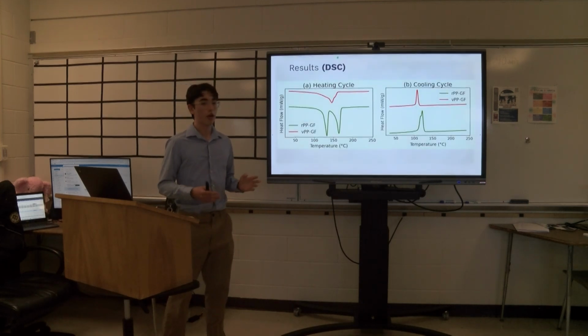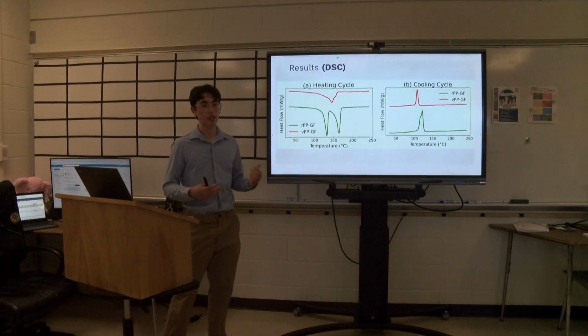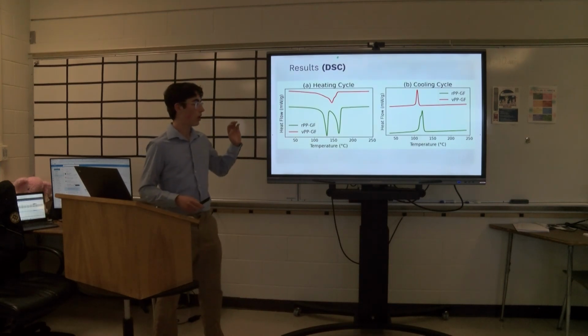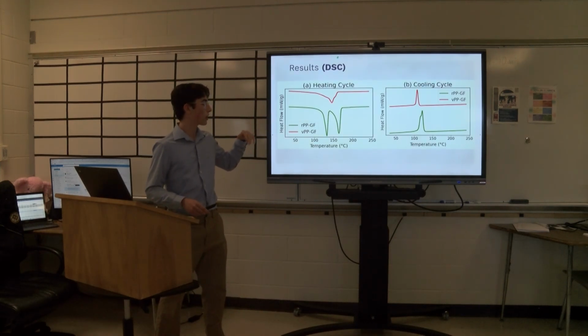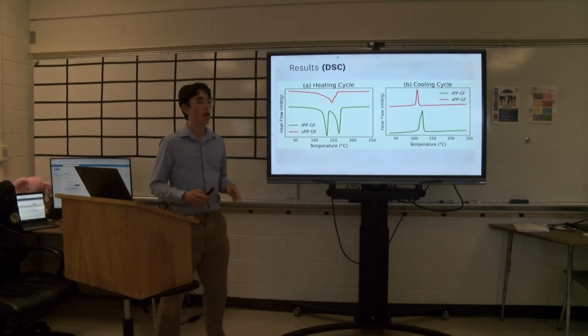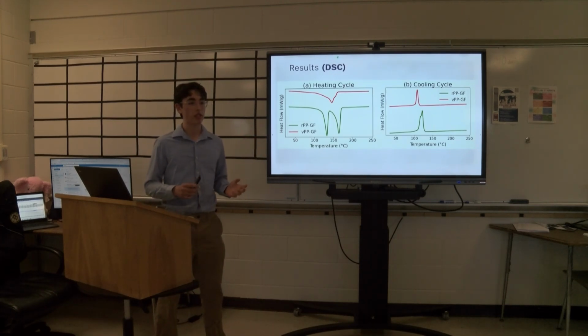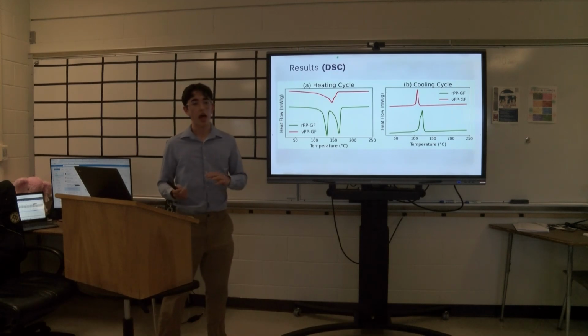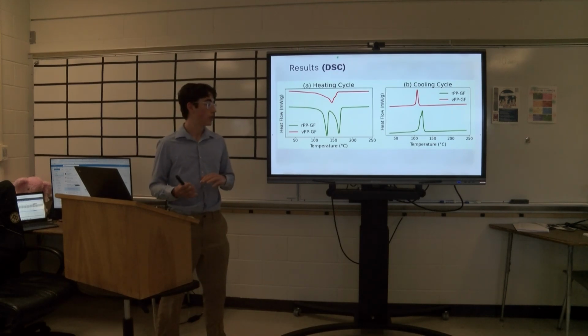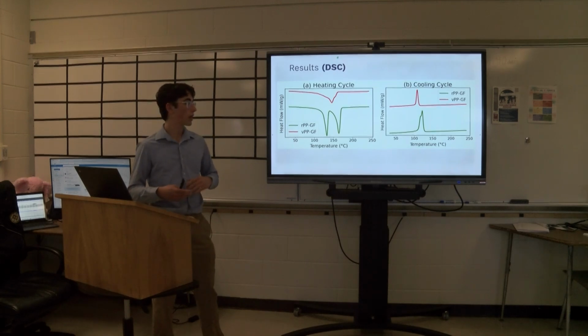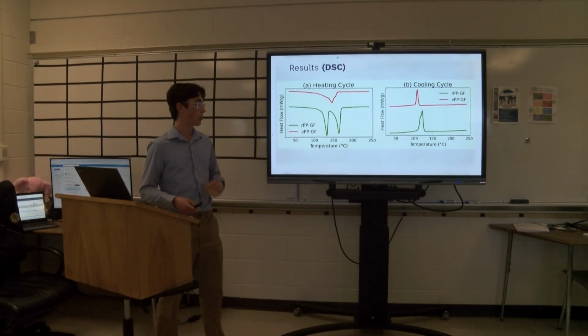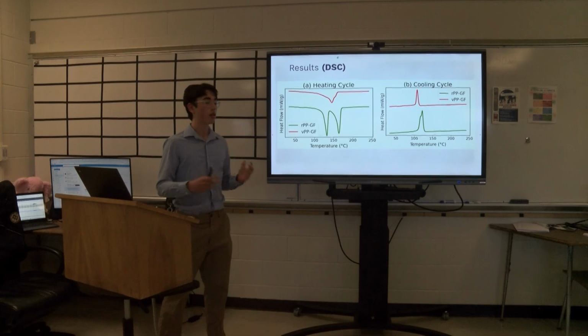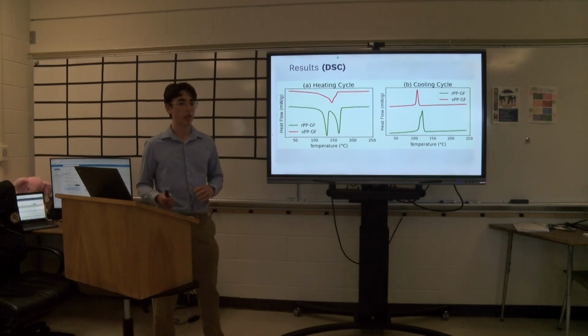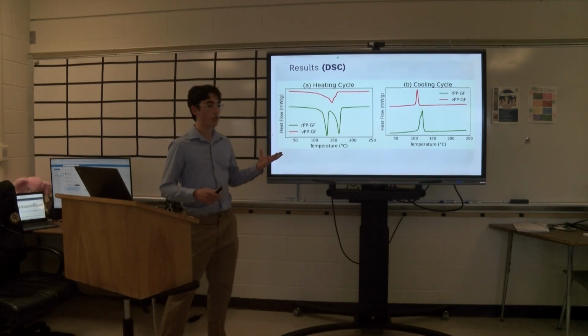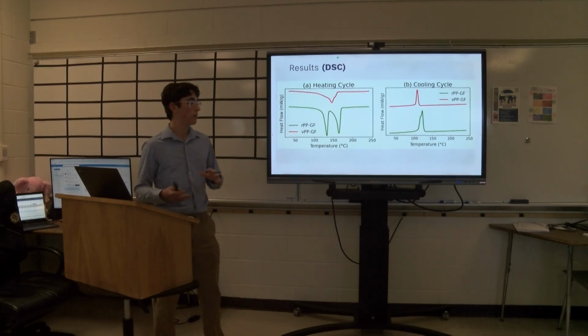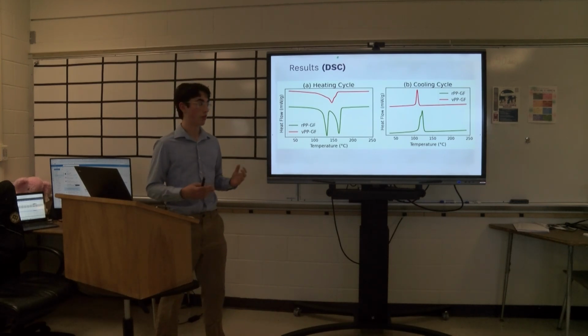So for DSC, the most apparent thing you'll see when looking at the graphs generated is that the melting curve for the recycled material has two peaks. And this is something usually seen in composite materials, but you wouldn't really expect this in this case, as the only expected components of PPGF are polypropylene and glass fiber. And glass fiber actually has a much higher melting temperature than polypropylene, so you wouldn't even see it on this graph. So that means there's another material present in the composite that wasn't indicated by the manufacturer. Now, if you look at their melting temperatures and compare them with other accepted values, you begin to develop an idea of what the other material could possibly be.